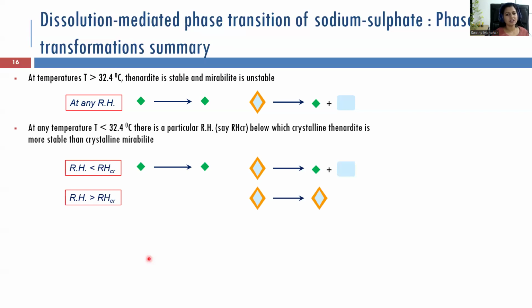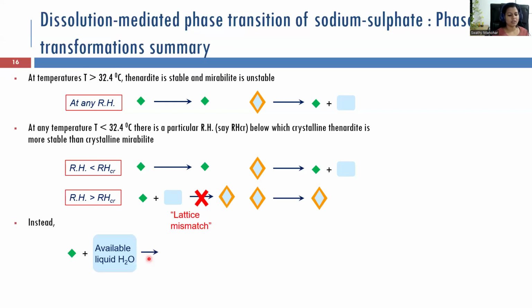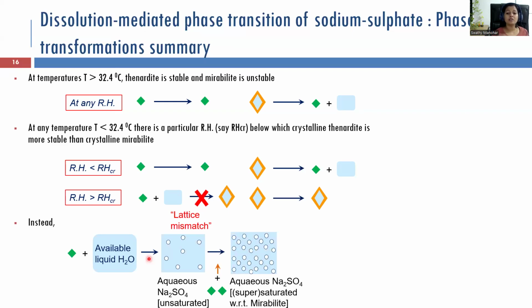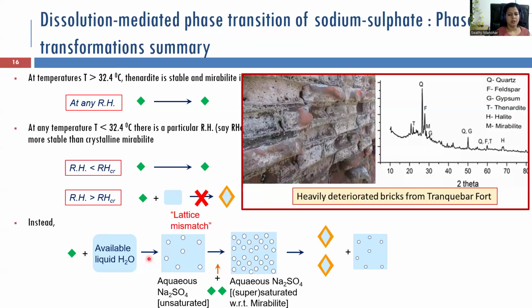But then thenardite cannot directly convert to mirabilite because of lattice mismatch. What actually would happen is thenardite will get dissolved in water and form aqueous Na2SO4 solution, and more thenardite will come and dissolve in that and form supersaturated aqueous Na2SO4. When it is supersaturated, you would get mirabilite crystals precipitating out of it. Now you would have more mirabilite crystals in the system, which are larger in size, which are expansive in nature, which would create crystallization pressure at the pore wall, and it would cause damages.